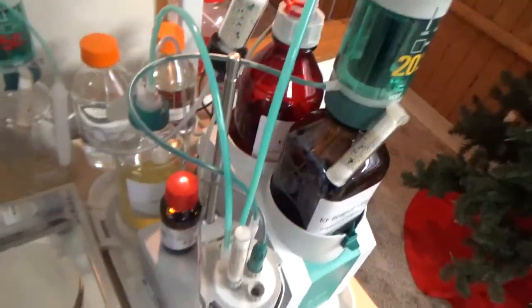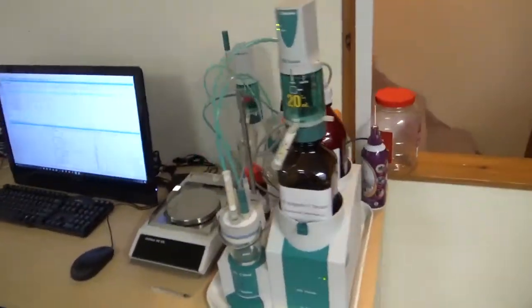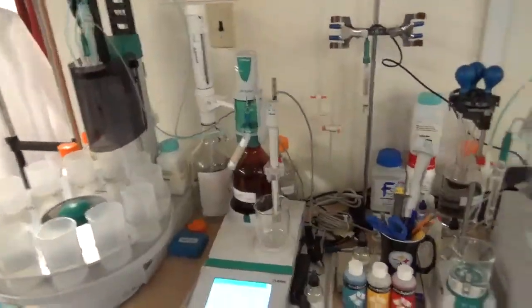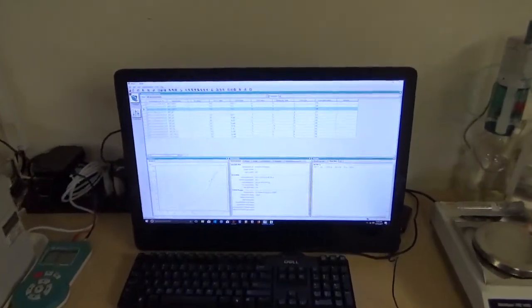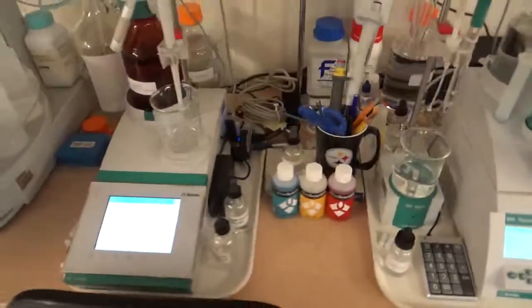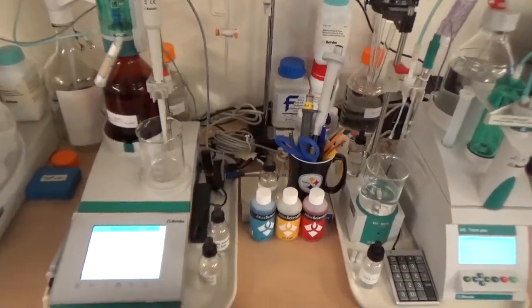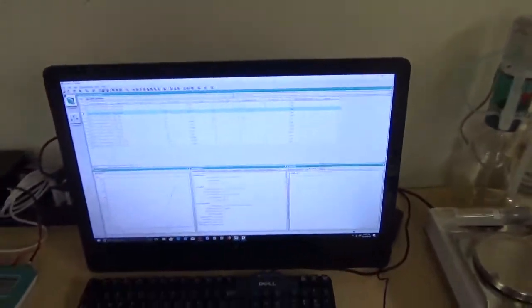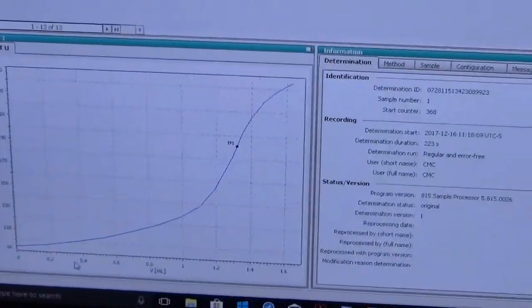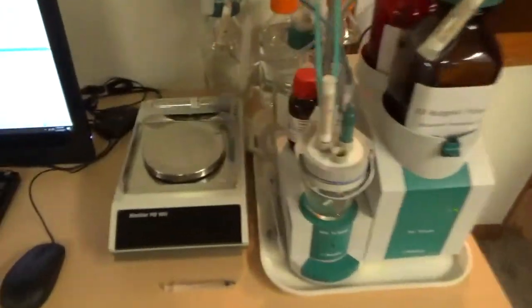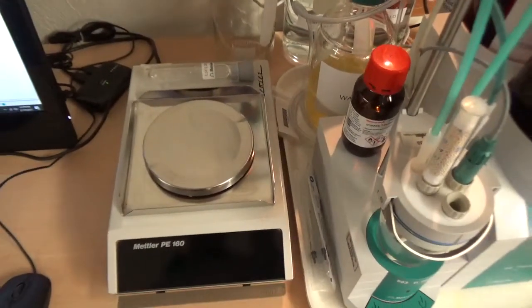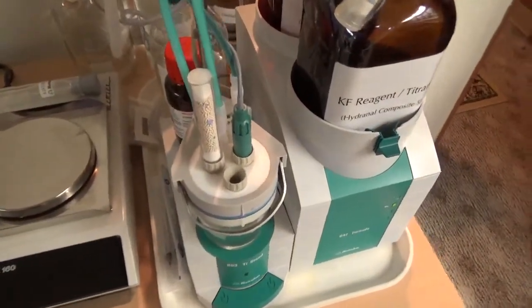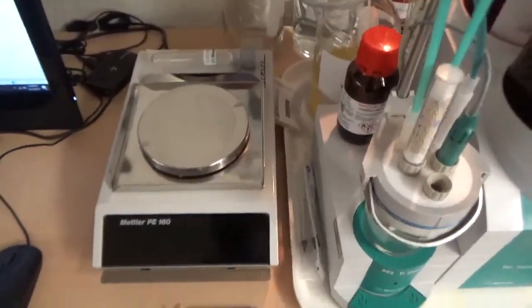The Karl Fischer titration with the 841 Titrando we use with Tiamo software, and when we do the potentiometric titration for chloride or acid-base titration, we use Metrohm's tiBase software where we collect the data. These instruments are quite independent to generate the titration plot, and once the titration is done, the result is automatically transferred to the tiBase software where you get the data, the titration curve and the results. For the Karl Fischer titration, we also need a balance to determine the sample weight before and after dosing the titrator with the sample.